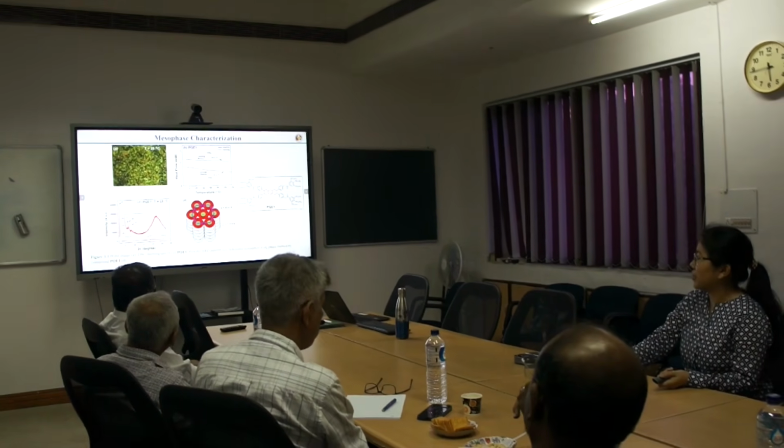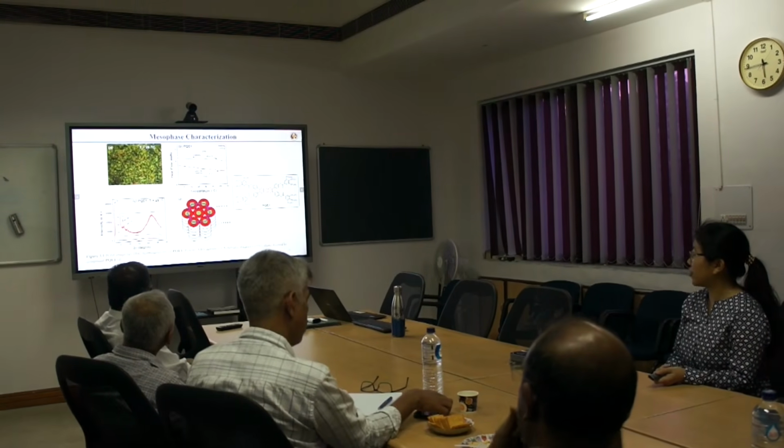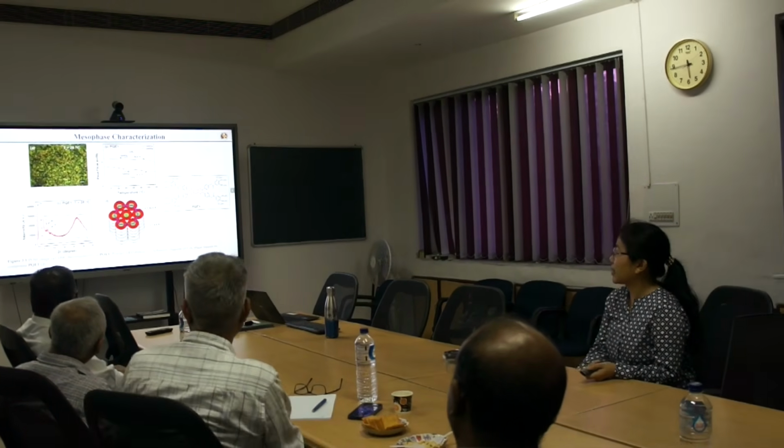From the data, we could obtain the lattice parameter of 43.4 angstrom and a packing distance of 4.4 angstrom. And this molecule, at 28 degrees Celsius, was found to have the number of molecules per unit cell to be 2. So that means in a core there are 2 molecules forming 1 core. However, for PQE2 and PQE3, these both have 2 alkoxy chains on the 1 phenyl group, but vary in position,